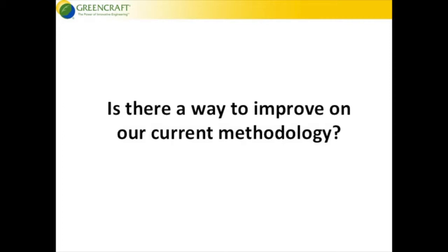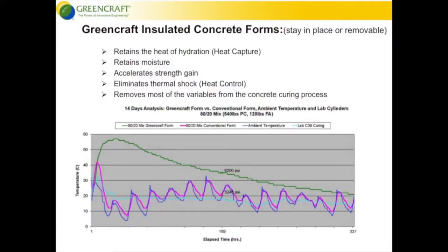So is there something that you can do about this? Can we improve this? When we were developing these composite insulated concrete forms, we wired them with the same IntelliRock, filled them up with concrete from the exact same batch, just moved the pump hose over. You can see here that in that insulated form, the temperature keeps rising well beyond the temperature peak of the conventional form. We get about 56 Celsius in about 36 hours, and we stay there for half a day, and then gradually, about 2 degrees Celsius a day, we lose heat to come to the same temperature as the environment in about 14 days.